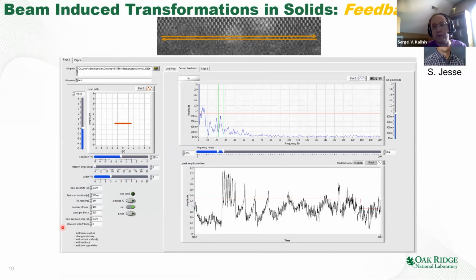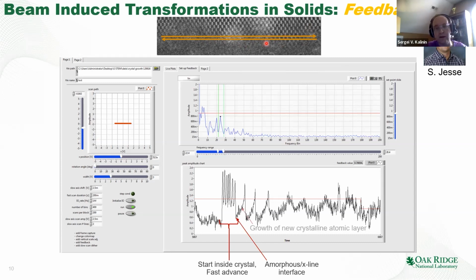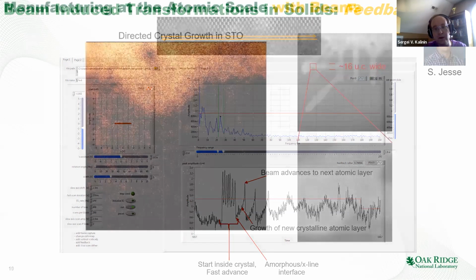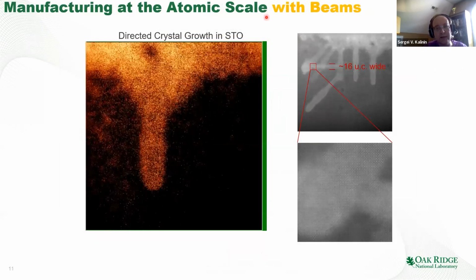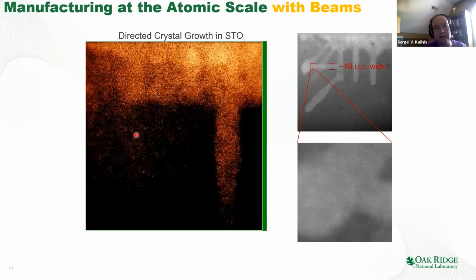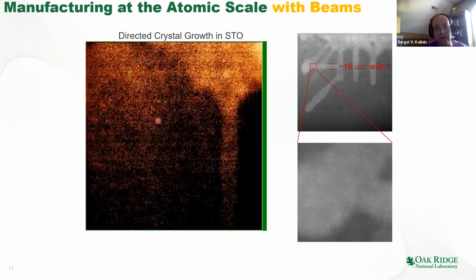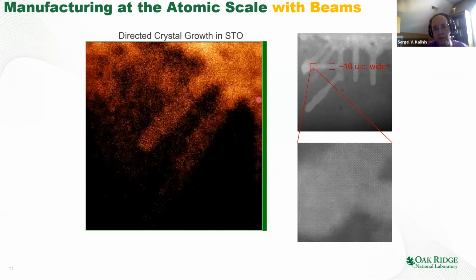The question becomes, can you make it automated? That was our first foray into the automated experiment, in a very primitive form, a long time ago. We said, look, we can scan the material, and we can make a very simple feedback circuit that detects the crystallization within the amorphous layer, and it tells the microscope to advance to the next position to induce crystallization once the crystallization event is detected. So this is how it works. This is the microscope which automatically creates the strontium titanate patterns, switching between the imaging and crystallization mode. And this is the end result.